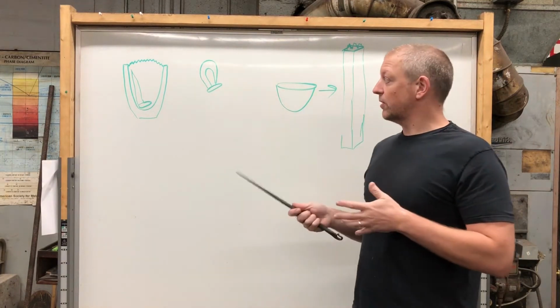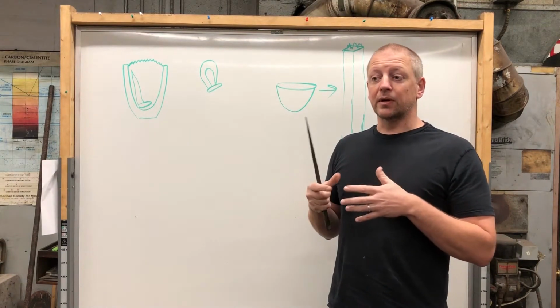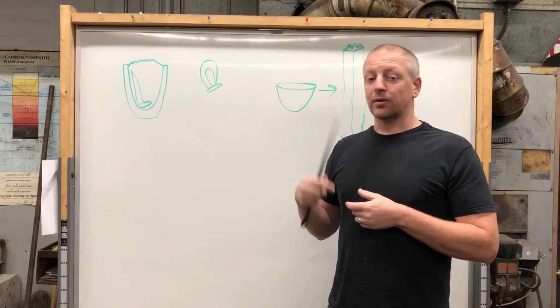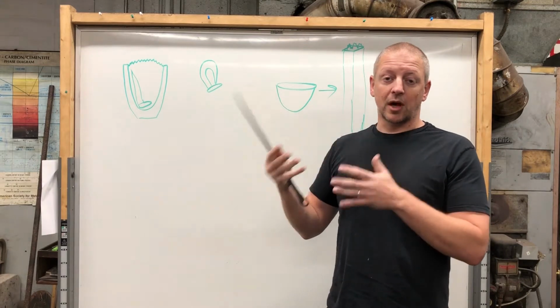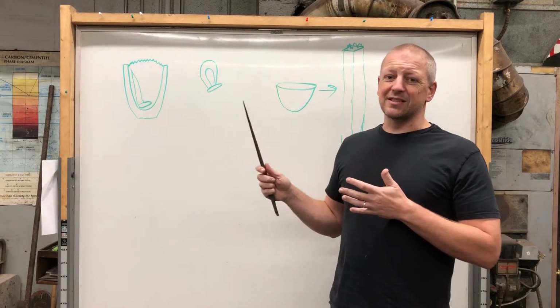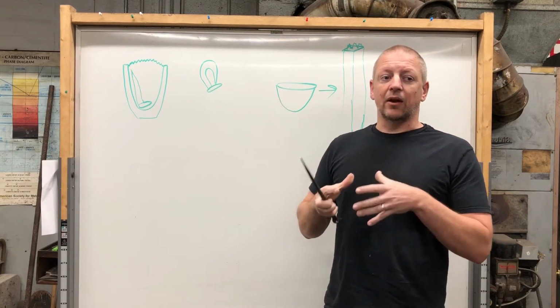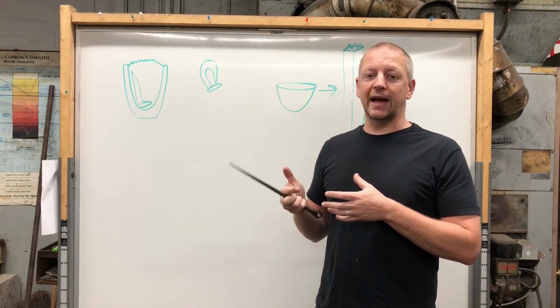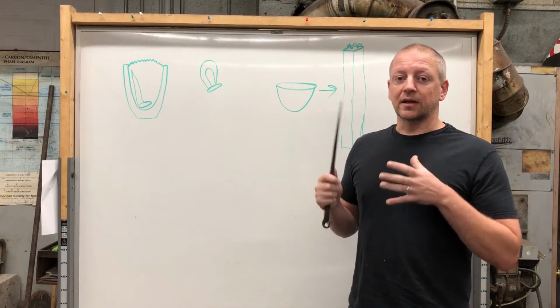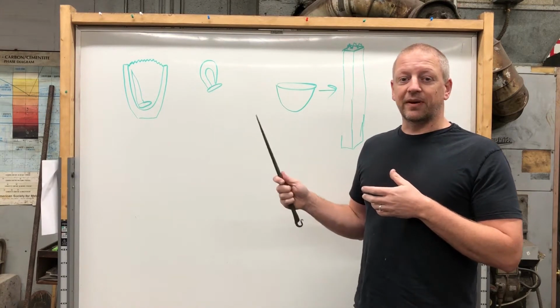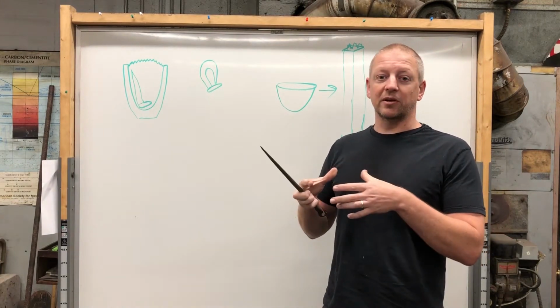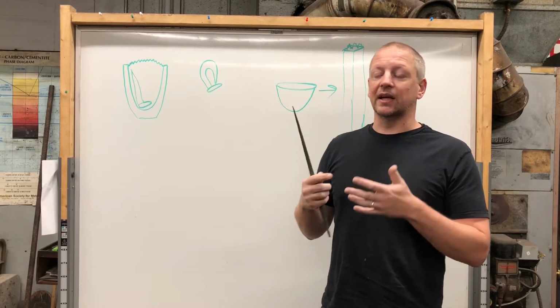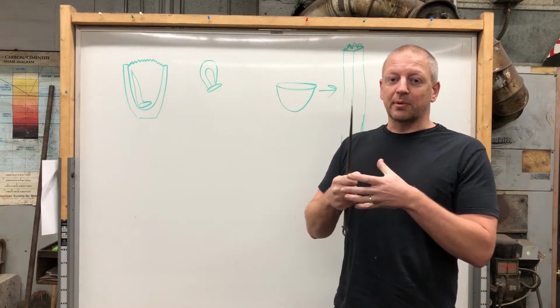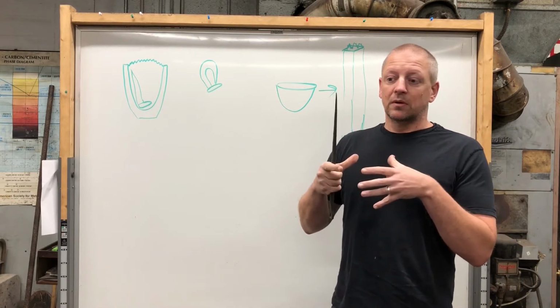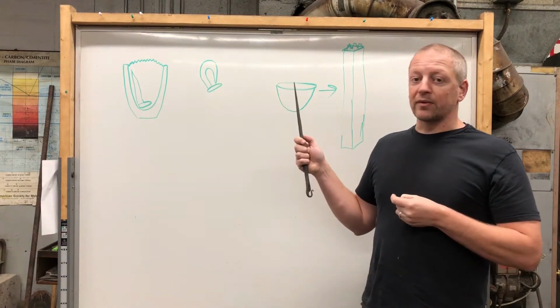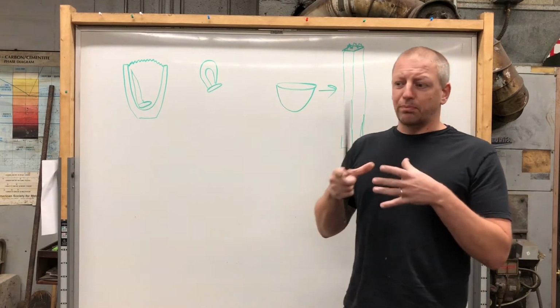It does two things. First, it combines with some of the carbon that I had put in. Therefore, I end up with a lower carbon content. Rather than that carbon becoming part of the steel, it becomes carbon monoxide and floats away. The other thing is that when the steel is liquid, it can dissolve quite a bit of gas, in this case a lot of carbon monoxide. However, as it begins to solidify, it can no longer hold that, and you get a similar effect to, say, champagne, where suddenly all this carbon monoxide, carbon dioxide that has been in solution starts to bubble out during the solidification process. I just ended up with a very porous ingot.